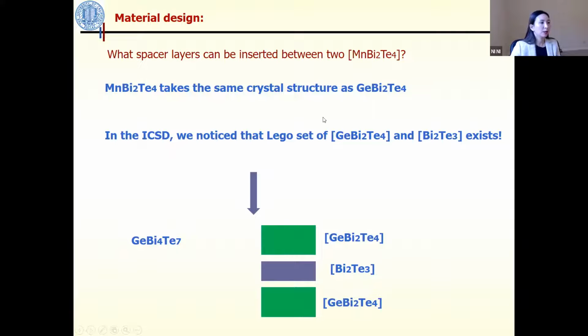So in the ICSD, we noticed that a compound of this germanium 124 and 023 actually exists. Germanium bismuth 4 tellurium 7 actually exists. Then the natural question is, it seems like 023, which is the bismuth 2 tellurium 3 layer, should be able to work fine as the spacer layers.